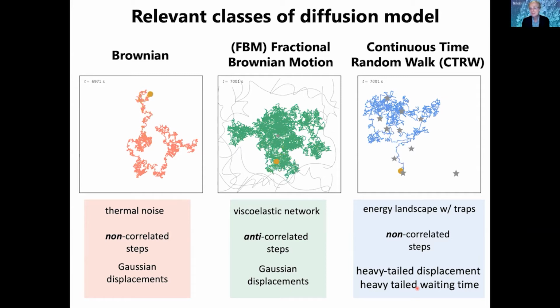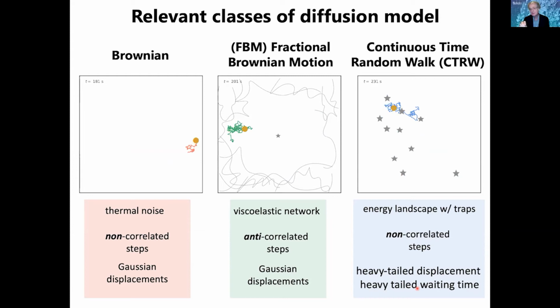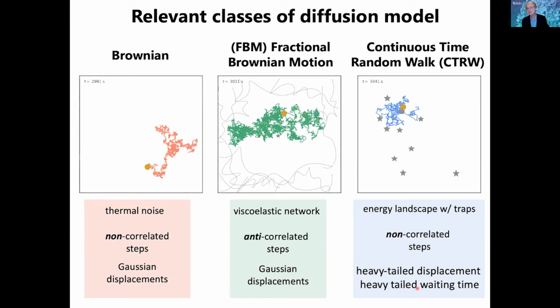Another model is what's called continuous time random walk. Imagine, if you will, that the surface somehow has a few places that can very strongly bind a particle. In that case, we might see a trajectory where a particle stays in one position for quite a while, and then all of a sudden it makes a big jump and leaves. And those steps will now no longer be correlated, and indeed they will have what's called a heavy-tailed non-Gaussian displacement and a heavy-tailed waiting time.